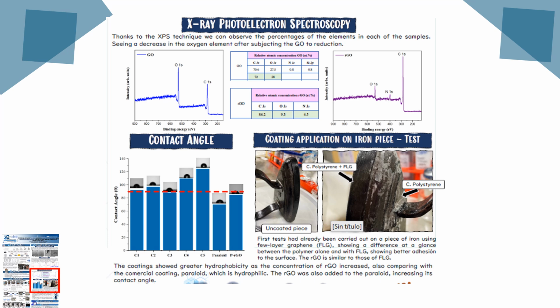In this graph, we can see that almost all samples meet this criterion, except for those based on Paraloid. We observe that as the concentration of RGO in the material increases, the hydrophobicity also increases. Due to the properties of graphene, in the case of sample C3, a higher value was not obtained because the surface was very uneven, making the use of the goniometer difficult. But we prepared more samples with a better surface, so we hope to get better results later.